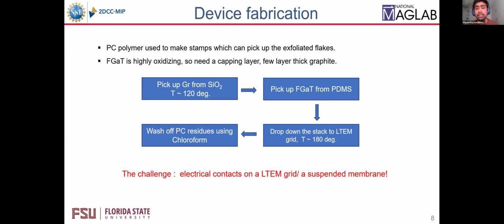So what we planned was that I would make the stacks and transfer the stack to the grid, and later we can do a top contact. I dropped down all my stacks onto the LTEM grid by applying a temperature of 180 degrees Celsius. At 180 degrees Celsius, this PC polymer will completely melt and my stack will be transferred to the grid. Later we will wash off the polymer residues using chloroform.